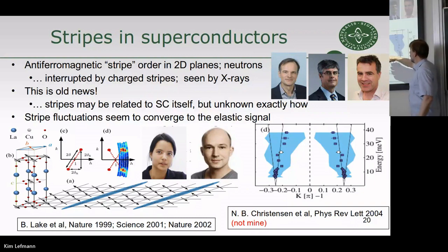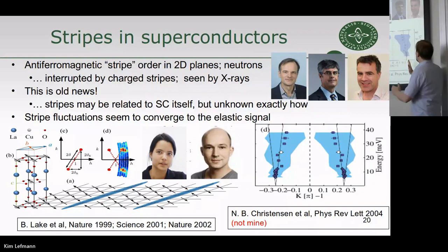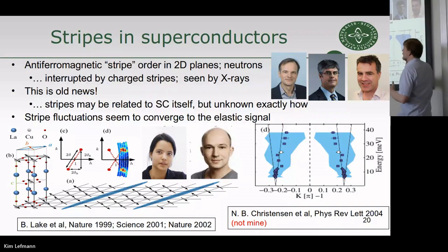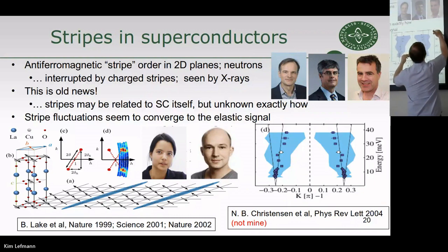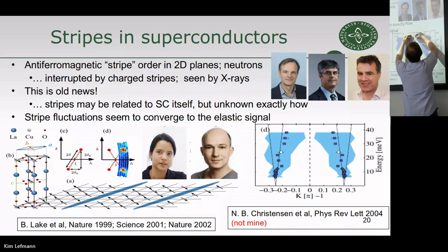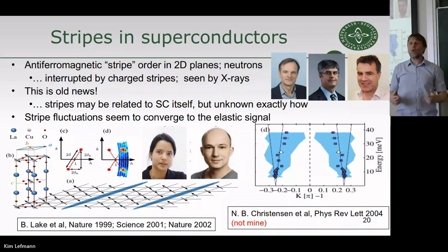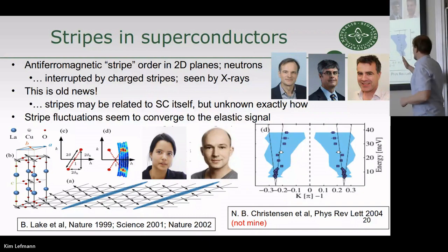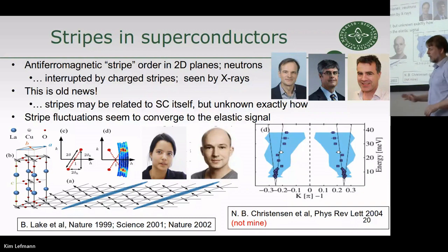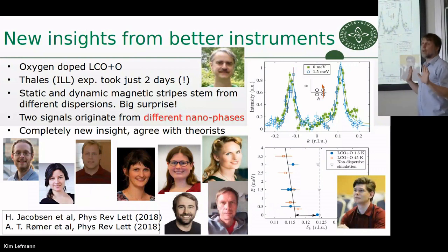What we also found is the dispersion, so this is energy 10 to 40 millielectron volts. The dispersion is vertically upwards initially, and then it bends over, and when you go just above 40, it kind of completely merges into something strange, and then the dispersion goes outwards. That's known as the hourglass feature, if you're into this field. But most importantly, from what I'm showing now, it is vertical for the first 10 millielectron volts. So that was what we knew from year 2000.